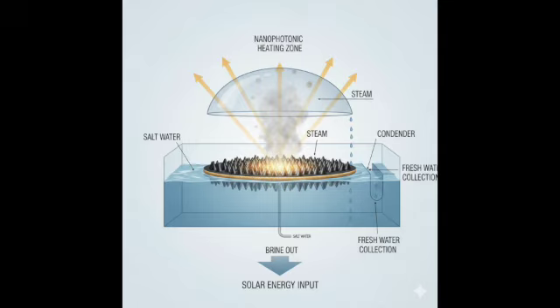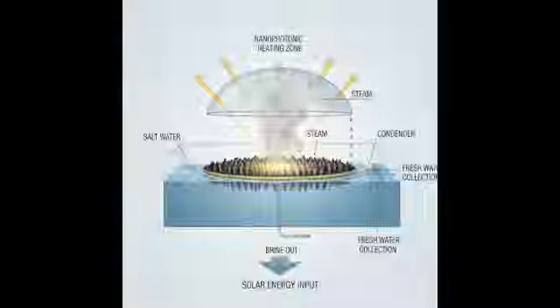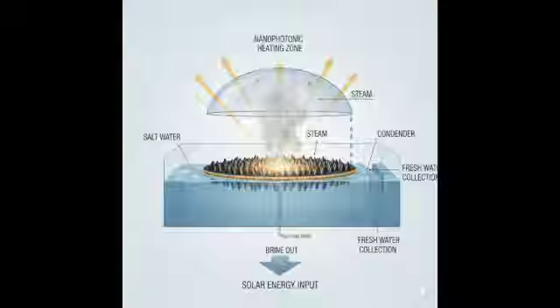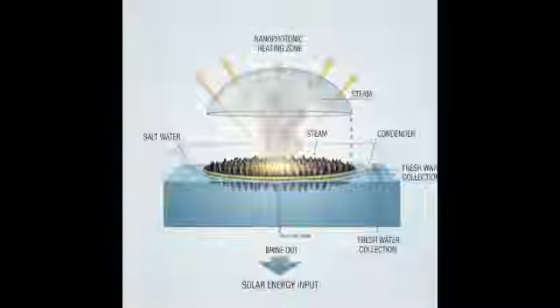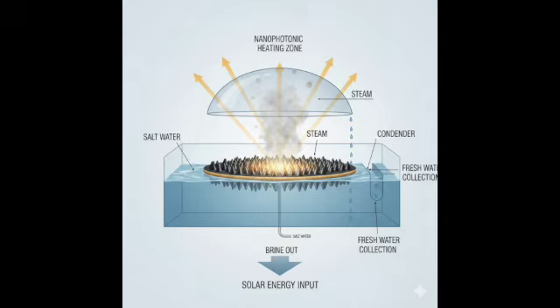Wow, so MD, even SPMD using free solar heat, might still need significantly more total equivalent energy input than RO, especially if you factor in pumping energy. That's often the case, yes. The thermal energy from the sun is free, but converting it and running the system isn't necessarily more energy efficient overall than highly optimized RO for clean seawater. So why pursue MD-SPMD at all if RO is so energy efficient? The justification hinges on MD's strengths. Its tolerance for very high salinity feeds where RO fails or becomes exorbitantly expensive due to osmotic pressure, its resistance to certain types of fouling, and its ability to utilize low-grade waste heat or solar thermal energy directly. It targets different, more challenging water sources.